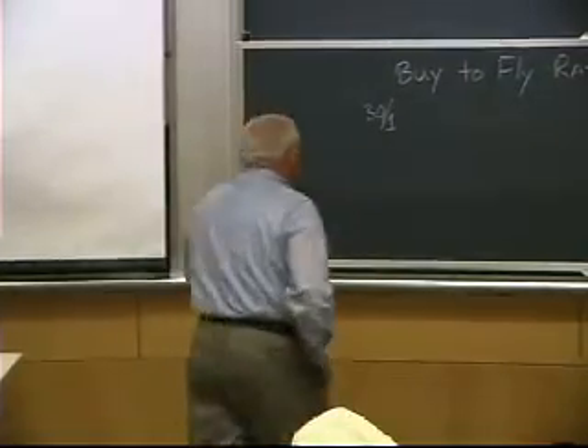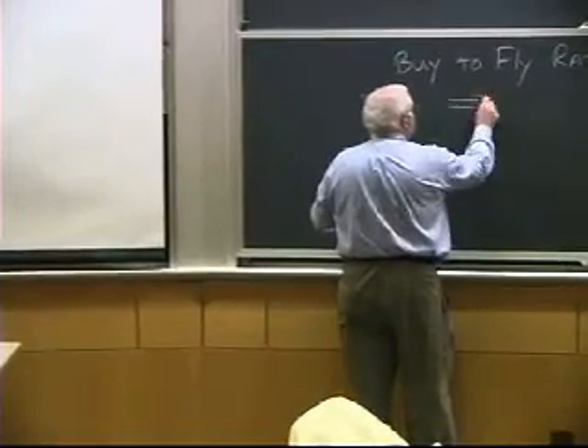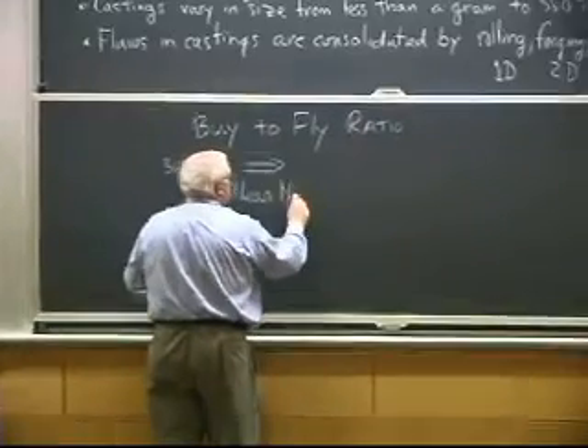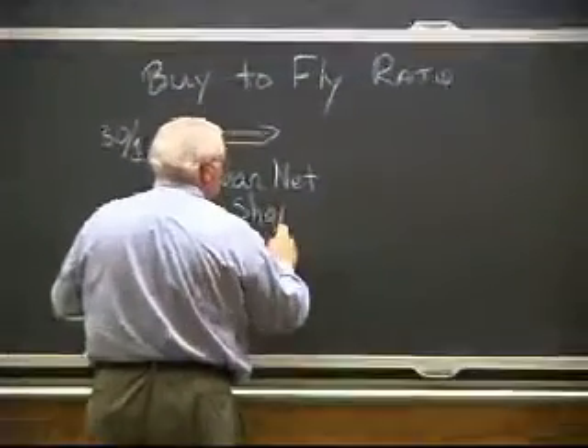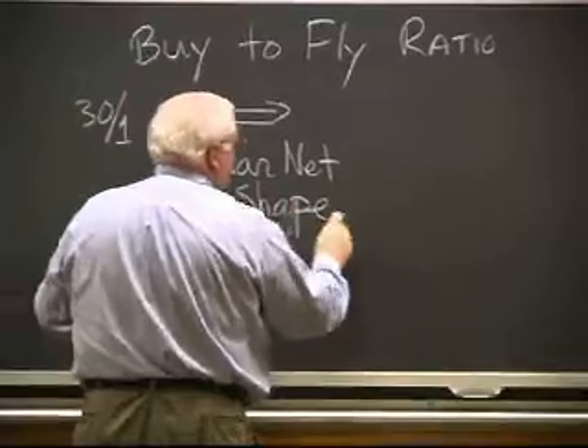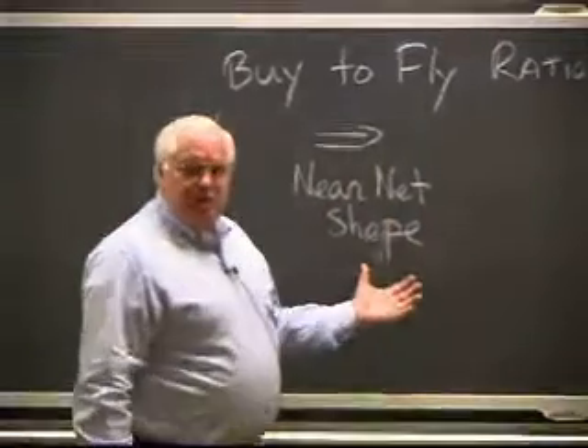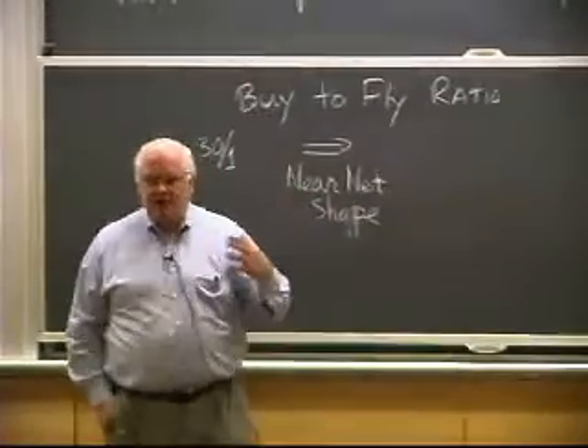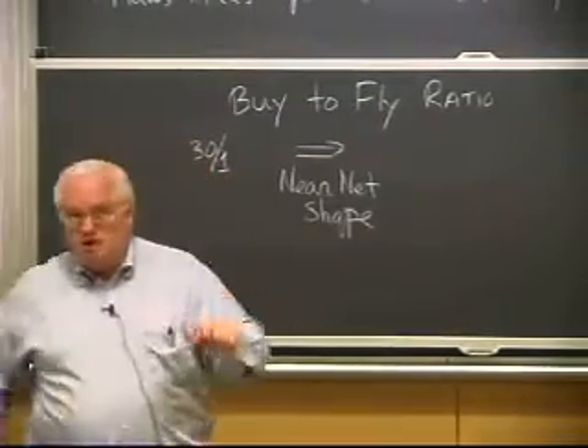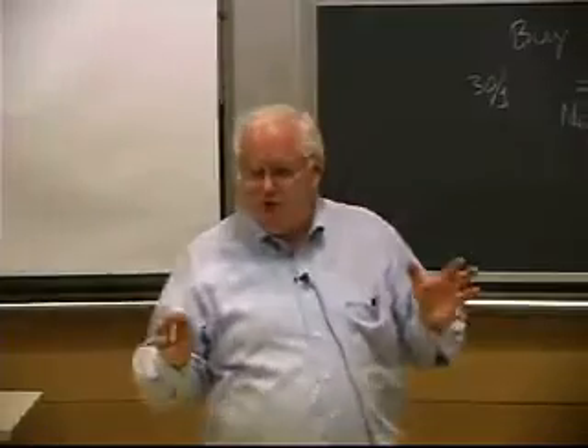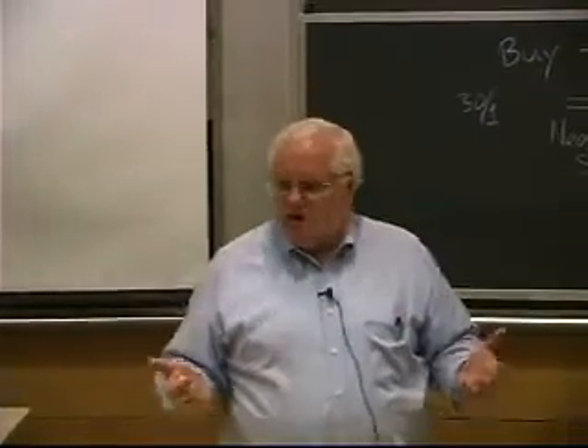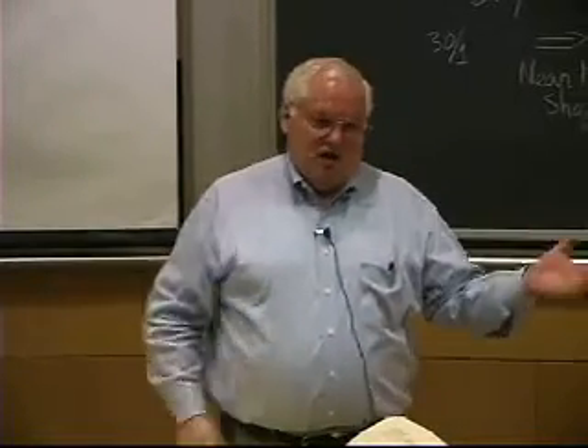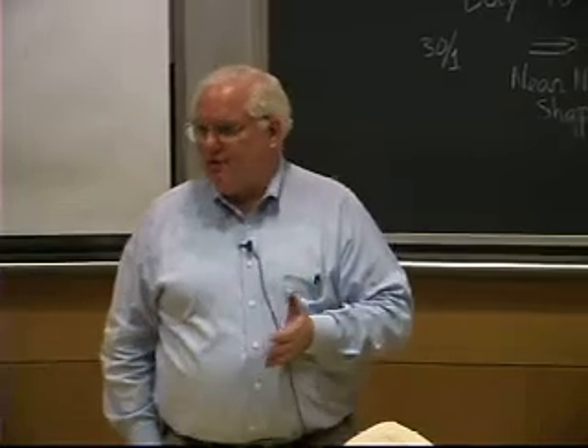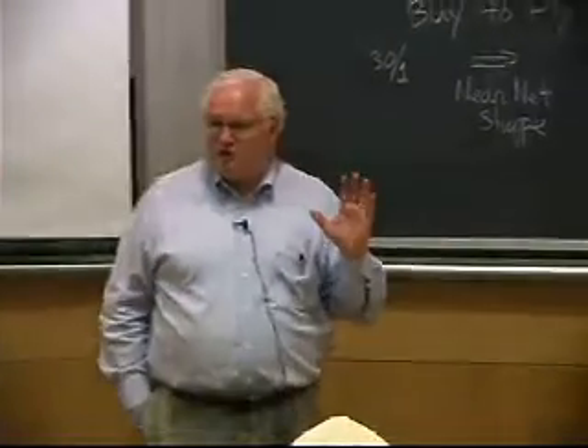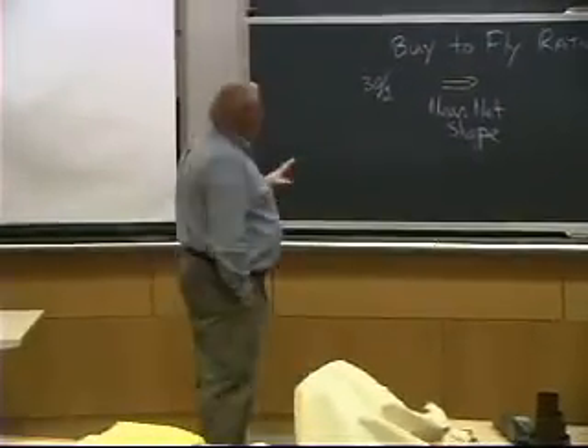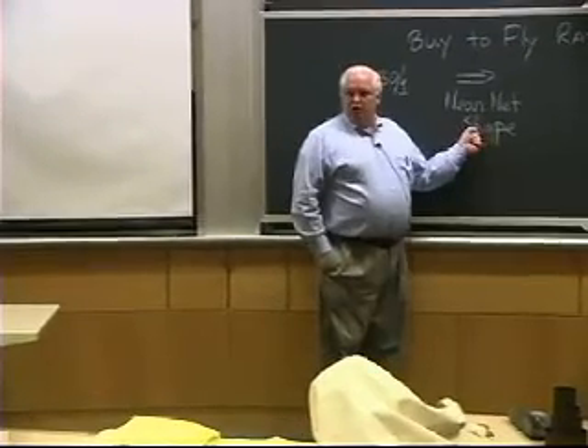So a big program in the 1980s and into the 1990s was near net shape. And near net shape went back everywhere. It was a huge program to look at the whole metal forming operation. Near net shape manufacturing, they went back to the casting operation. Could they cast things closer to net shape? And the dog bone structure at Chaparral Steel was not an Air Force program, but it was the same idea. If you're going to make an I-beam, you cast it in a dog bone shape rather than a rectangle. And Chaparral went from 29 rolling steps to about 10 rolling steps. They cut out 67% of their passes through the rolling mill to make an I-beam in the rolling operation by going to a closer to near net shape casting.